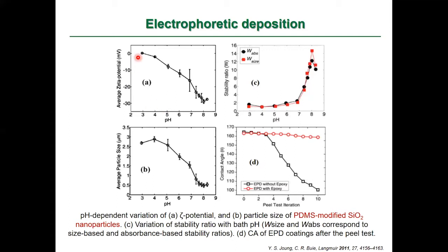You can see the average zeta potential varies with the pH, and this is a maximum zeta potential that they achieved in that study, and that corresponds to the most stable system. Colloidal stability is high there. That is also analogous to particle size. When the deposition medium was prepared, they also added epoxy into it. And when the coating has additional epoxy, you can see that the durability, the peel test performance of the epoxy coating, was high. That means the durability enhanced.